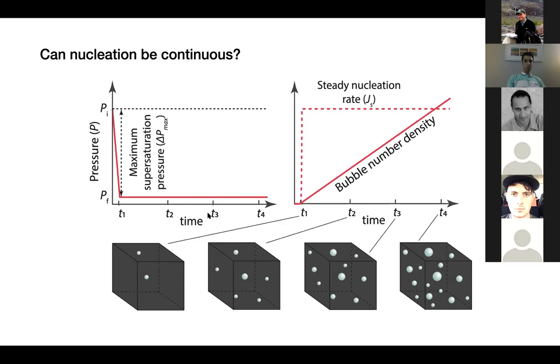The idea here was that as samples are decompressing, nucleation rate starts increasing. If we could just stop decompression before nucleation peaks and then the system reaches equilibrium, then nucleation must continue throughout the sample's annealing time. Bubble number density will increase proportional to nucleation rate, and by quenching them at different times, we should be able to see variation in bubble number density.